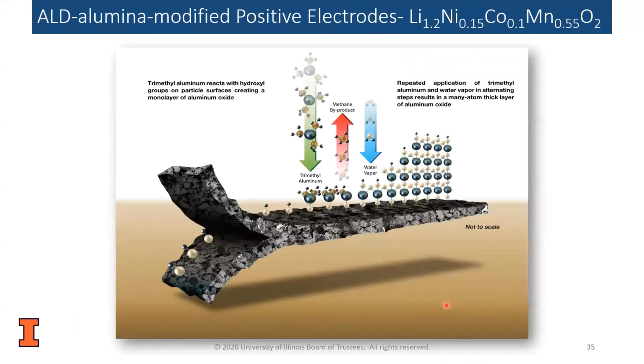So the next section is a group of experiments that, together with Argonne National Laboratory and the University of Illinois, we did some studies of the more advanced high manganese containing NCM. And so just to remind everybody, alumina, the ALD process, the surface is dosed with trimethyl aluminum, where it reacts with the hydroxyl at the surface and gives off methane byproduct. And this is self-limiting, then we add another layer of water vapor, form hydroxides, and then repeat with trimethyl aluminum, water vapor, trimethyl aluminum, and so on.